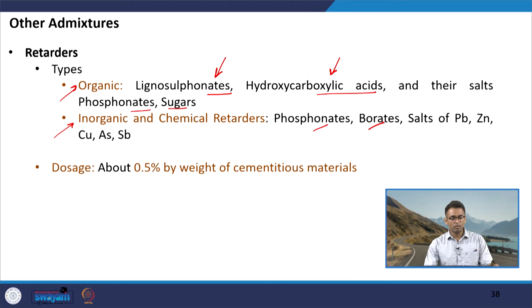The typical dosage of retarders used for concrete production to delay initial setting time is about 0.5 percent by weight of the cementitious material. Now let us move to the last topic in this module: geopolymeric cement, or more generally, geopolymeric concrete.